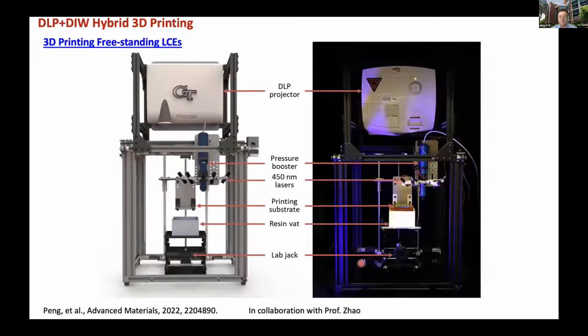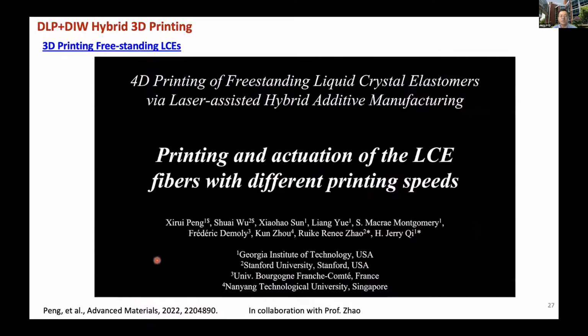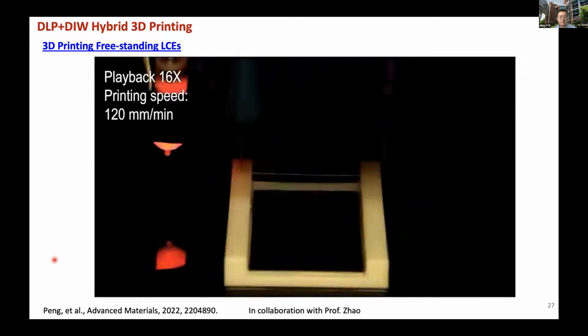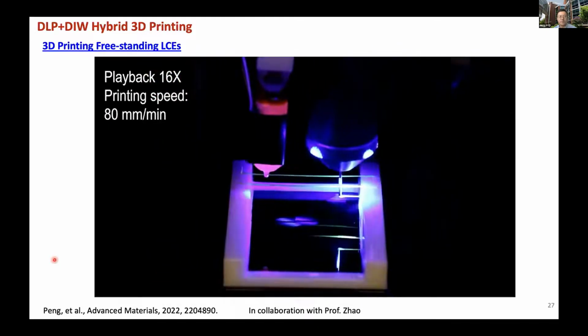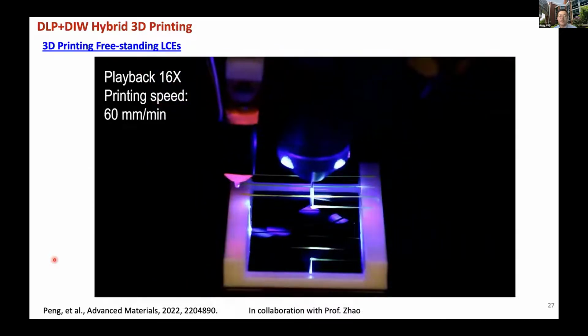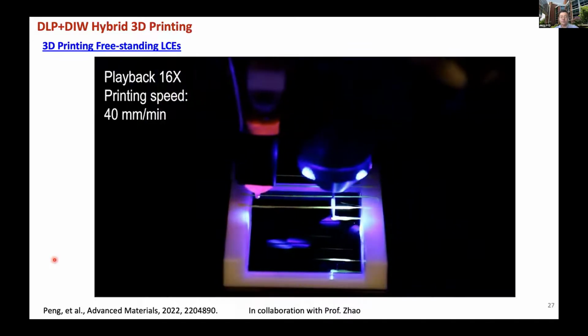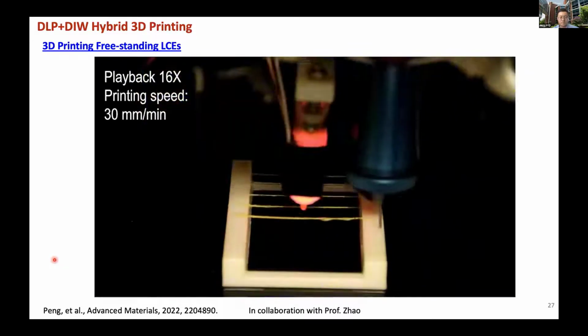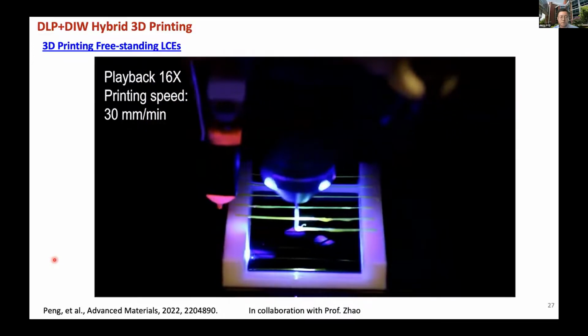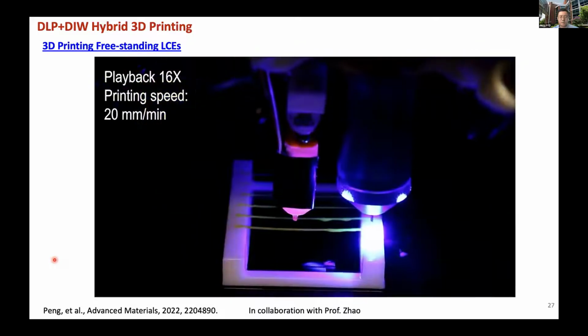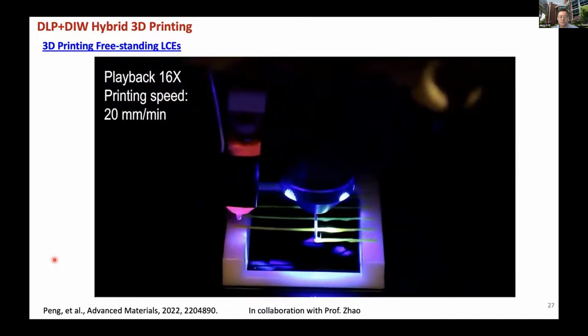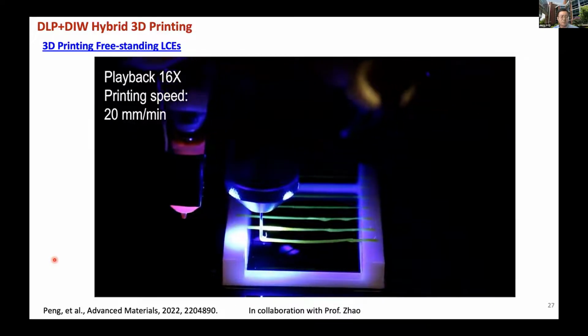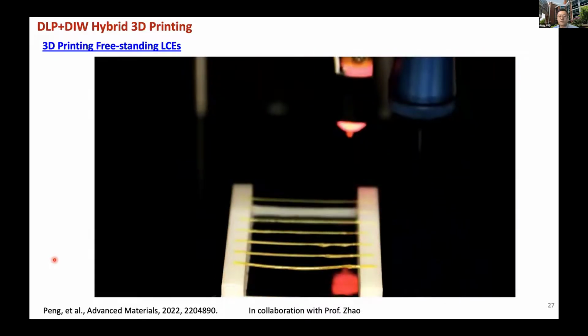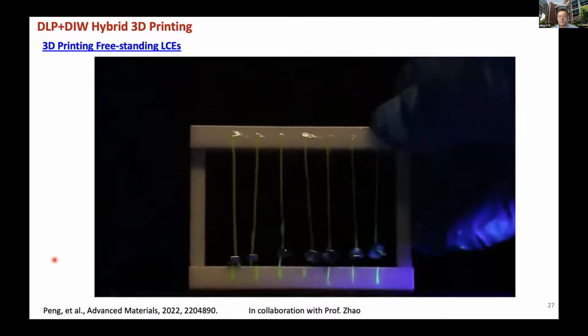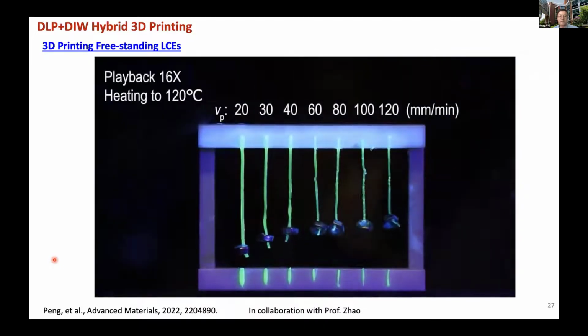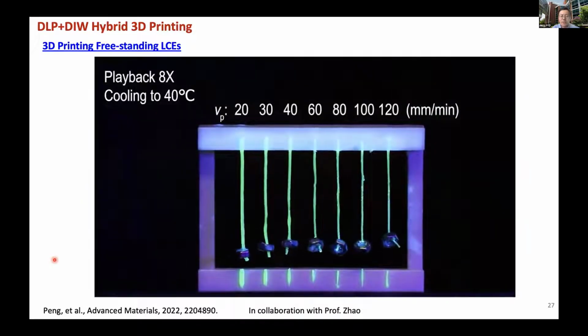So here shows the experimental setup, and here shows the printing process. This is one line. We did a study at different printing speeds. Here we're printing a line between two supports at different printing speeds. This last one is 20 millimeter per minute moving speed. After printing, we can demonstrate actuation. We just cut it and attach a small nut to it, and you can see the actuations at the different printing speeds.